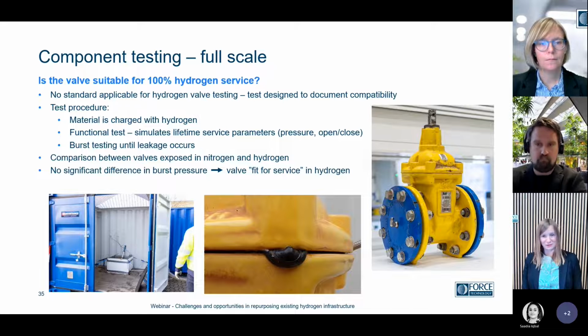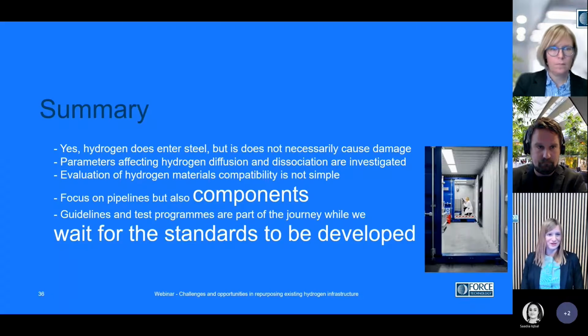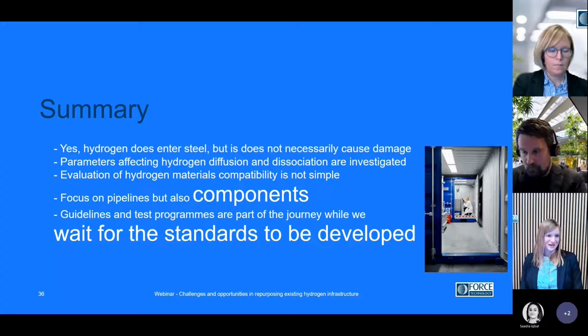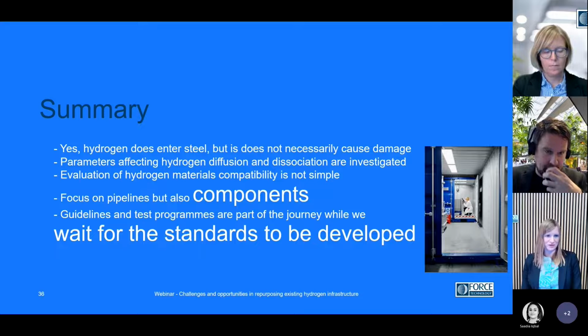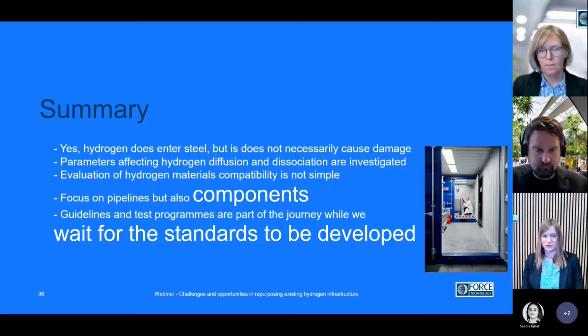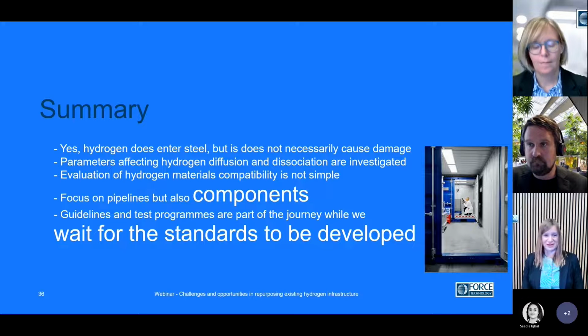But this is just an example of a test relevant to ensure the safe transition in hydrogen service, and something that we could not just look up in a table. So just to sum up, yes, hydrogen does enter the steel, but it doesn't necessarily cause damage. We have several parameters affecting hydrogen diffusion and dissociation at the surface, and these are currently being investigated.